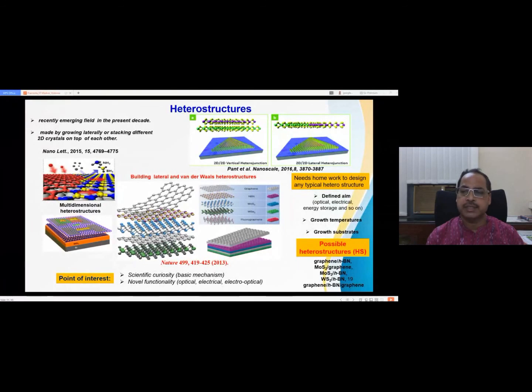Graphene growth on metal substrate. MoS2 is grown on the insulating substrate, so you cannot grow in situ. So what will you do? First you grow the graphene, then you transport it to a particular substrate. Then similarly you grow MoS2 on this one, and then this has to be transported to graphene, to make your graphene-MoS2 heterostructure.